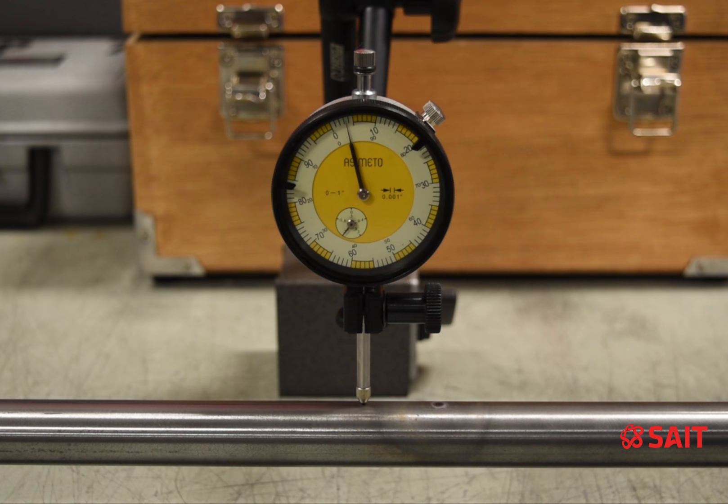Another thing to mention, I can repeat this process in more than one spot if the shaft has quite a large bow in it. If it moves 10 to 15 thou, we can heat multiple points to achieve a straightness that we want.